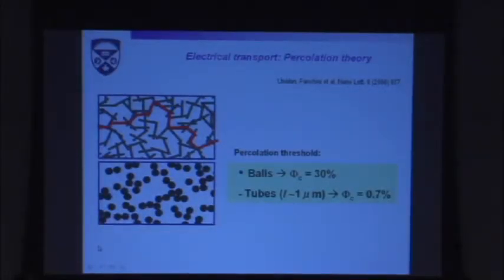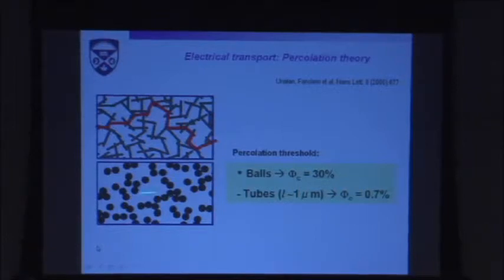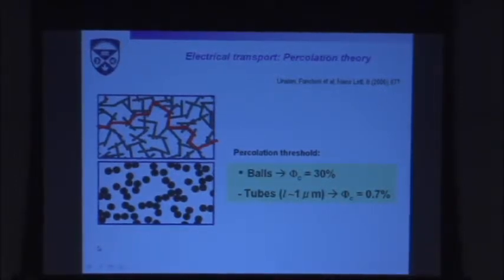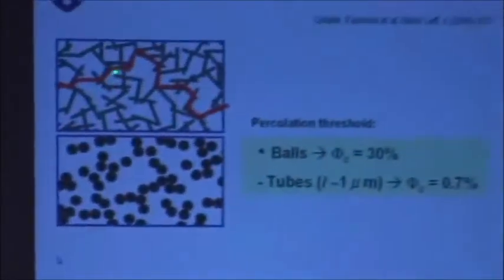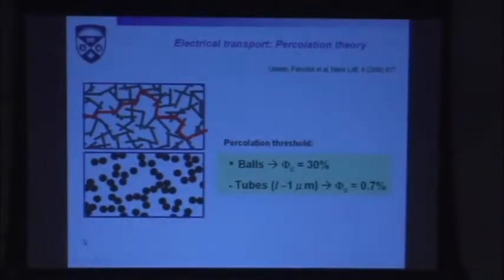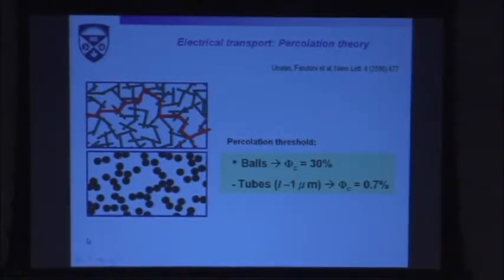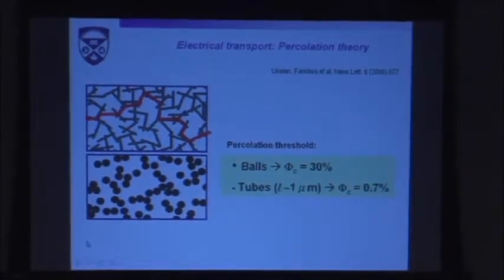So here we go. How is the electrical transport of this system controlled? You see, there are patchworks. So the first thing you can think to understand the transport in these materials is percolation theory. We had used it before for carbon nanotubes. This is, yes, the typical carbon nanotube thin film, spaghetti on the table, a percolation through sticks, or tubes, and the percolation threshold is very low. The percolation threshold is, by the way, the minimum concentration of nanotubes or flakes that you have on your layer that allows you to draw a continuous pathway along the film. How dense do they have to be to do that?